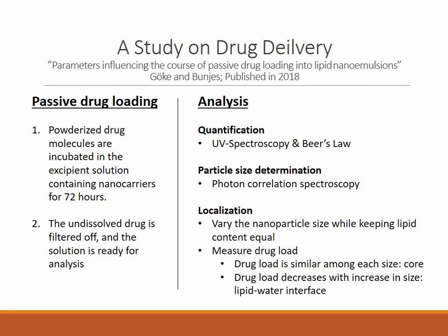Whereas if the drug load decreases as the size increases, you know that the drug is on the lipid-water interface, because with the larger size particles you have a decreased surface area, so you have less places for that drug to go.